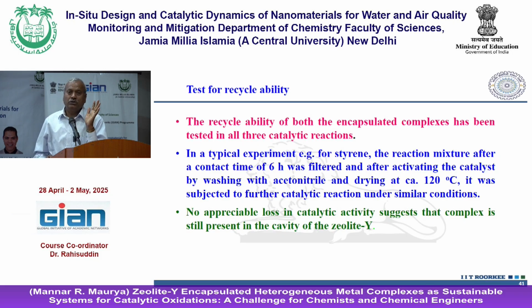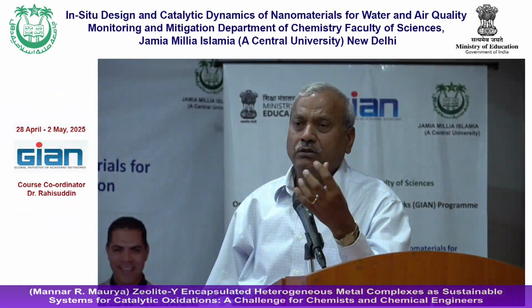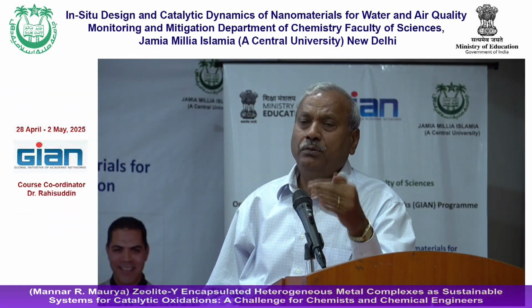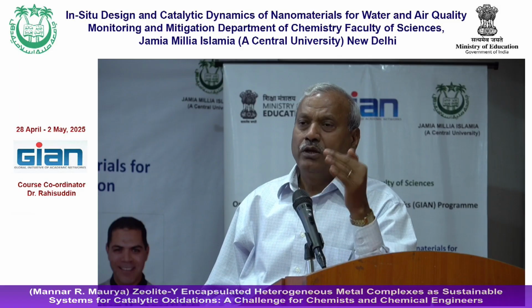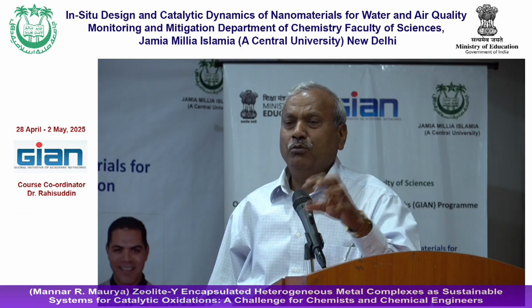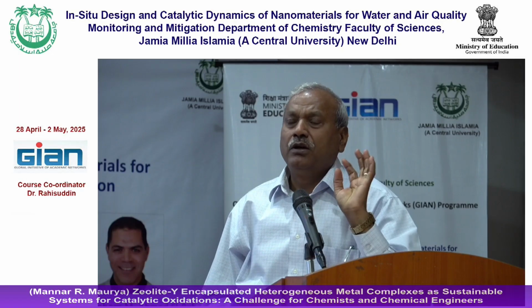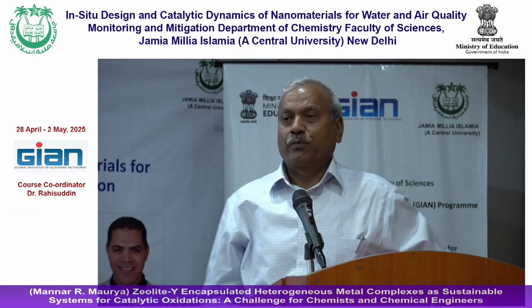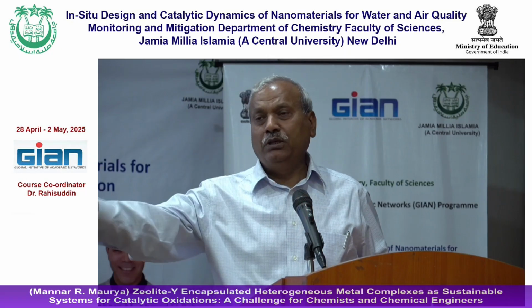A question may come that maybe the catalyst is coming out of the cavity into the solution and acting as a homogeneous catalyst, meaning part of the leaching occurs. To answer it, we took the zeolite encapsulated complex into the solvent where we do the reaction, and after the reaction, we removed the product, added more solvent, and filtered it, keeping the catalyst out.